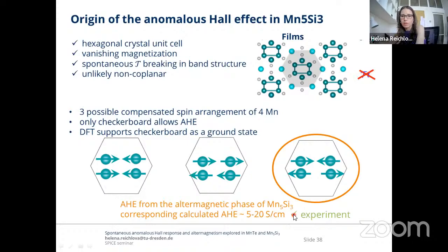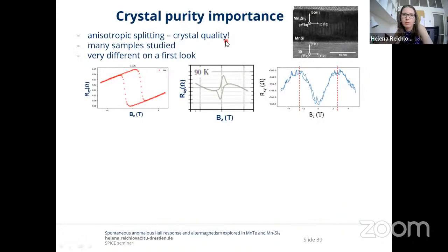I mentioned that this type of measurement, resulting from this anisotropic spin splitting, is also very sensitive to the crystal quality. This is something which we tested partly in our samples. We had at the beginning several samples which we measured in different labs by different people. And at first look, they look a bit different. We had some raw data measured which showed a clear response. Sometimes the response was a bit weaker. Sometimes the anomalous Hall response was entirely absent. And then we found that it can be actually very well correlated to the epitaxial character of the particular sample. This sample, for example, was fully epitaxial. This sample was mixed, having also some spurious phase. And this sample was polycrystalline.